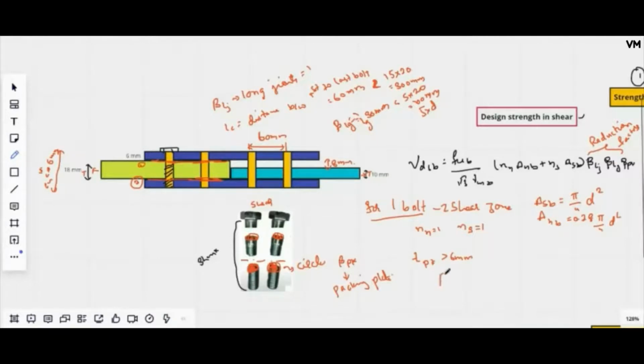So beta pk, the formula which we get from the code, will be 1 minus 0.0125 TPK, where TPK is the thickness of the packing plate. So there is some amount of shear which is reduced because of these packing plates, 0.0125 into 8, which is 0.9. If I substitute all the terms in the formula, which is 400 by root 3 into 1.25, n_n is 1, 0.78 times pi by 4 into 20 square plus pi by 4 into 20 square into 0.9.